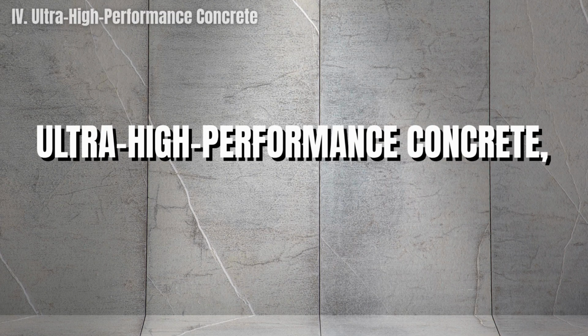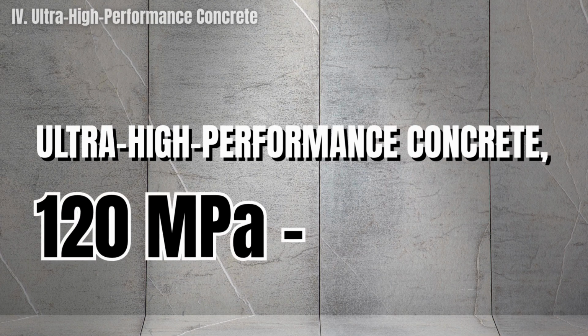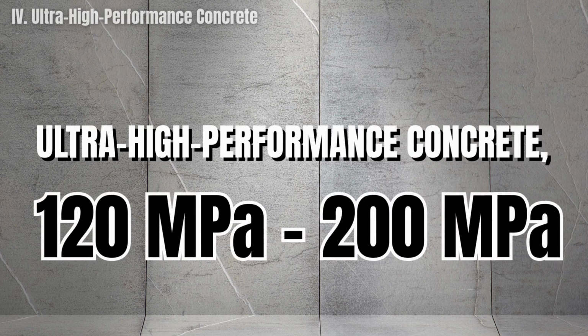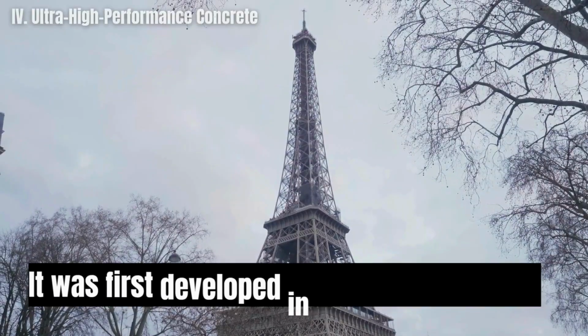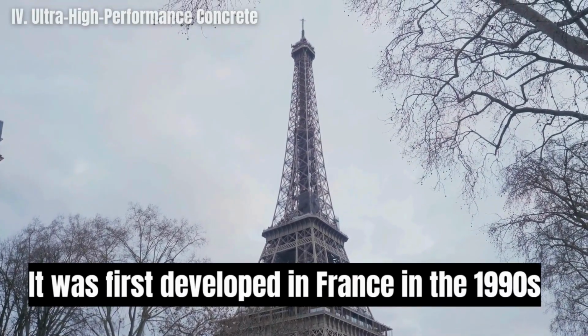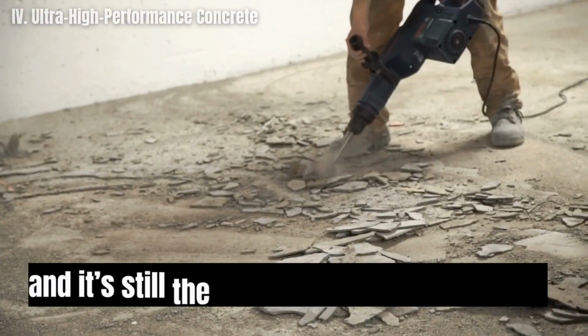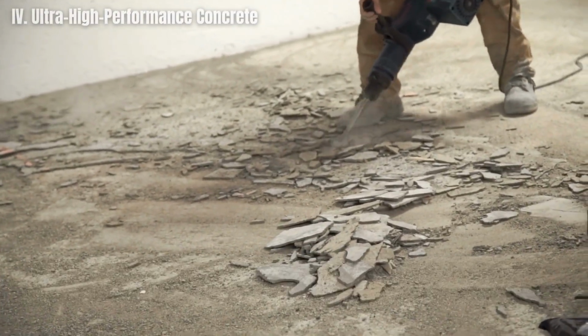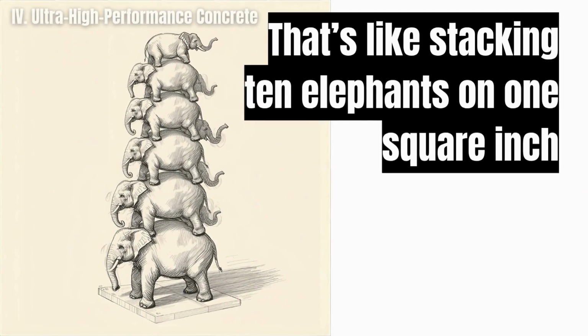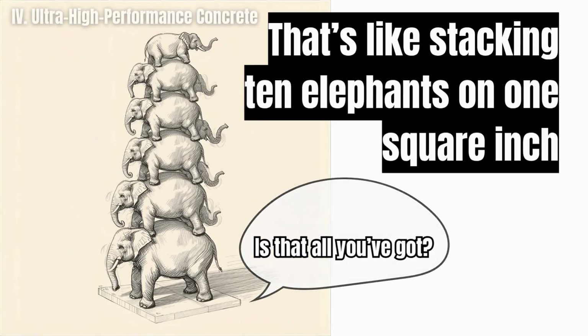Alright, time for the superstar, the ultra-high performance concrete or UHPC. We're talking about 120 megapascals and sometimes even 200 megapascals. It was first developed in France in the 1990s and is still the gold standard for toughness. That's like stacking 10 elephants on 1 square inch. And the concrete saying, "Is that all you got?"